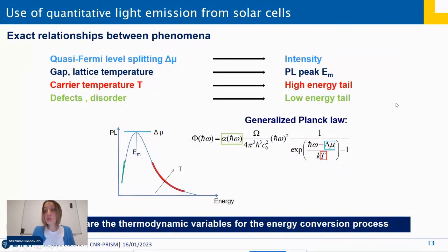But on top of that, we also work on the modeling. What we try to do is really to obtain maps of physical parameters. For instance, we can extract a lot of information from a PL spectrum. The intensity of the PL is related to the quasi-Fermi level splitting, the PL position to the gap of the material, the high energy tail to the carrier temperature, and this is particularly important for hot carriers, for instance, and the low energy tail to defects or disorder inside our semiconductor. How can we locally quantify these parameters? By fitting pixel by pixel the calibrated data using the generalized Planck law. I will show you later some of these maps.